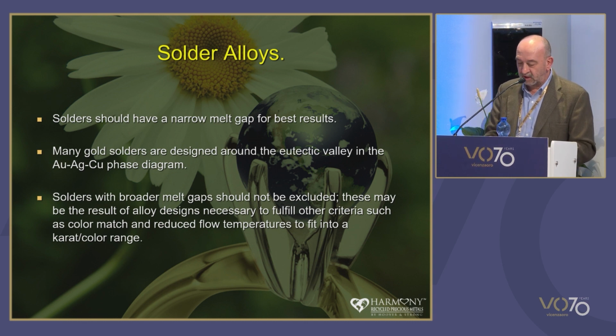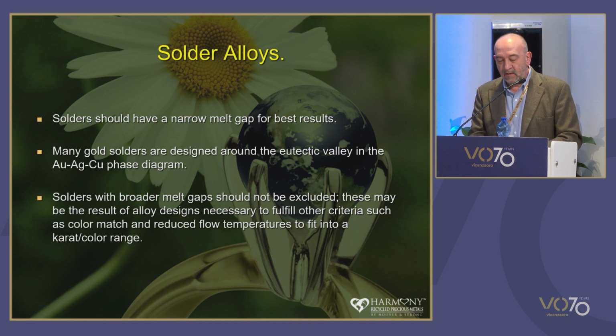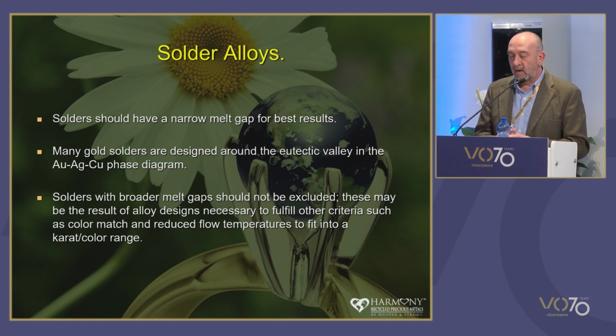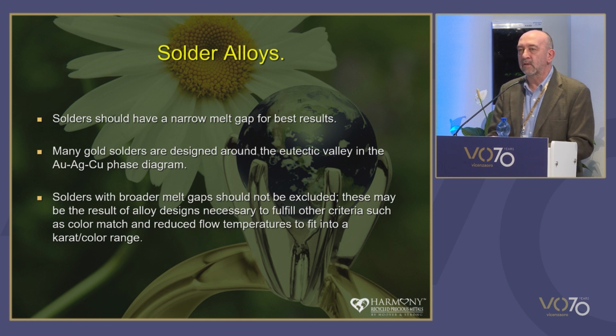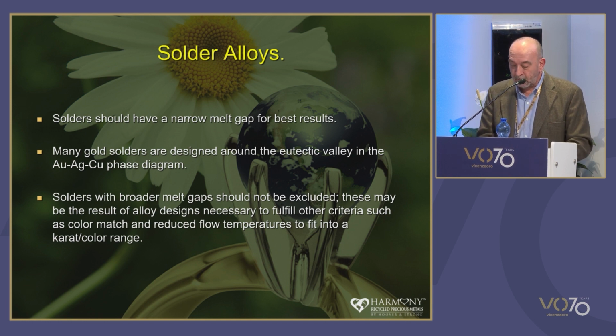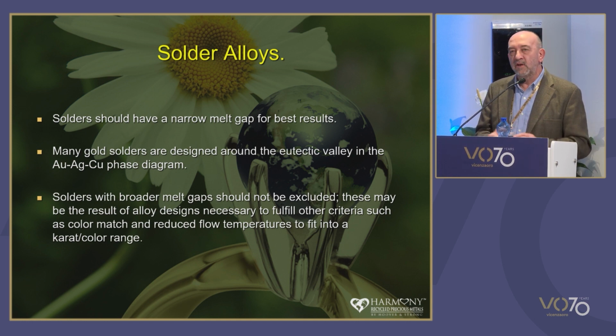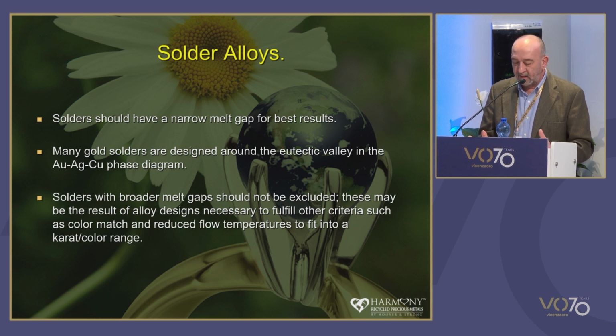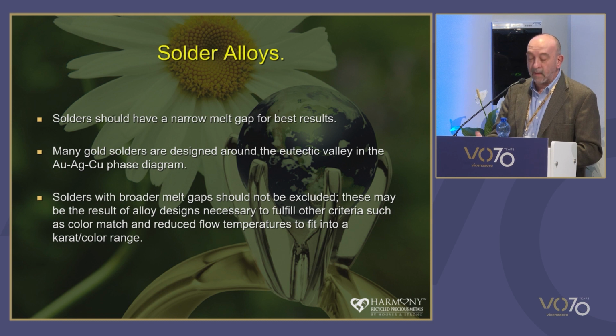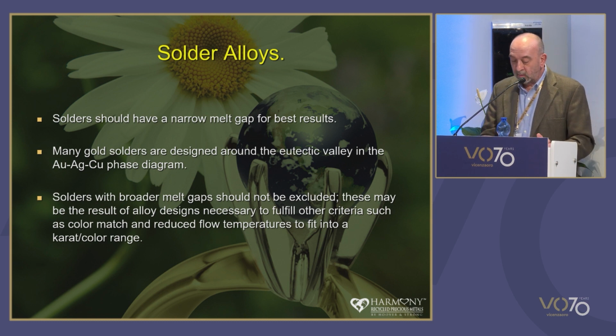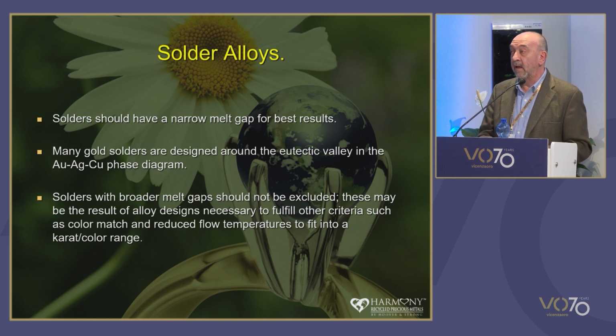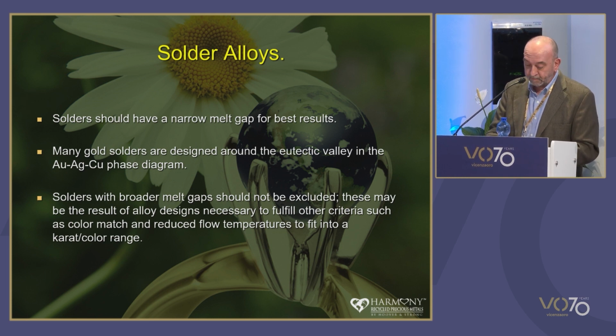As a general rule, easy and extra easy solders tend to be inferior to medium and hard solders as far as color match goes, particularly when you're talking about yellow gold solders. The elemental additions you have to put in there to depress the melting point, such as zinc, indium, tin, gallium, and in the US, cadmium, are all commonly used. These tend to affect the color, particularly when you're looking at yellow solders, and they bleach them.